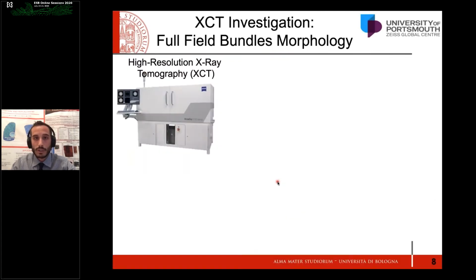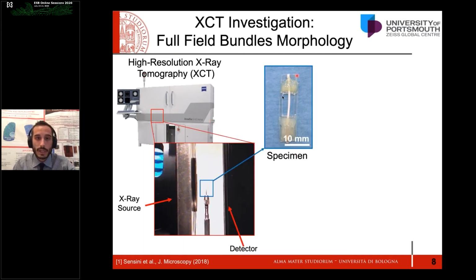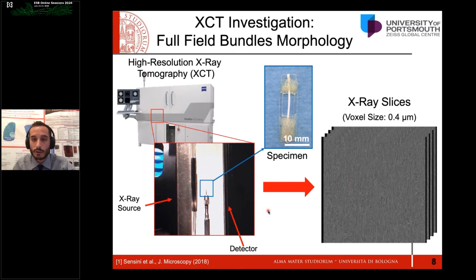For this reason, in collaboration with Professor Gianluca Tozzi and Dr. Alexander Cao at the University of Portsmouth, we optimized several high-resolution X-ray tomographic protocols to study, with submicrometric voxel size, the full field morphology of our bundles, developing dedicated setups that allowed us to reduce as much as possible all the artifacts, for example micro movements, increasing the overall resolution of our scans.